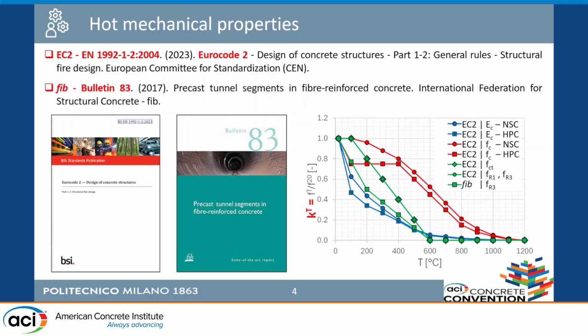So this curve represents what EC2 suggests for high-performance concrete. This decrease here is the opposite of what Dr. Wiley showed before. Why did this happen? Because in that case, we were looking at the residual condition, so after heating, while this is what EC2 means for the hot condition during heating, so the difference is the vapor pressure. In this range, we have a lot of pore pressure. This means that we have tension inside the concrete due to the pushing of the vapor, and so we have a decrease of the compression that we can measure during the hot test. This is a quite tricky phenomenon, because typically, if we measure the compression in residual condition, we see a gain in compression because of the rehydration, like a hot curing in the end, if we remain at 200, 300 degrees C.